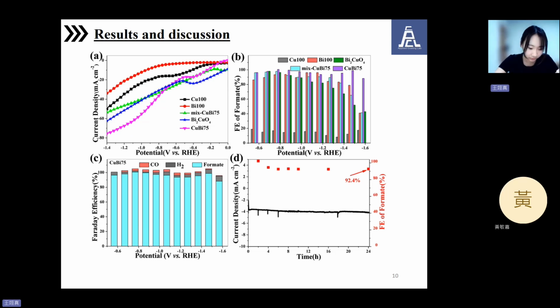In Figure C, the product distribution of CuBi75 shows excellent selectivity toward formate, with negligible CO or H2 detected. Figure D confirms its long-term stability. After 20 hours of continuous electrolysis at -0.77 V, the current density remains stable, and the FE for formate stays at about 92.4%, indicating excellent durability.